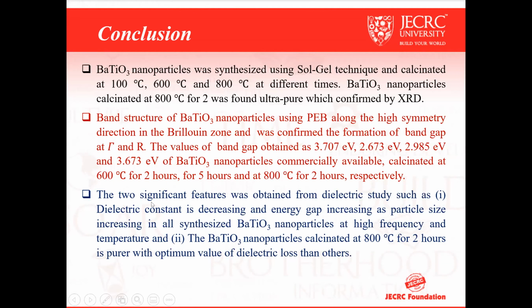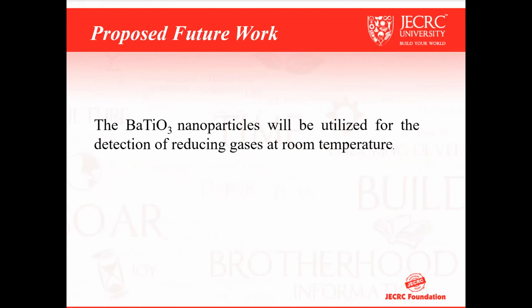The major conclusions drawn from the dielectric study: the dielectric constant decreases and the energy band gap increases as the particle size increases in all synthesized barium titanate nanoparticles, across frequency as well as temperature. And second, the barium titanate nanoparticle calcinated at 800 degrees centigrade for 2 hours is very pure and has an optimum value of dielectric loss compared to the others. On the basis of this, the future work is that this nanoparticle calcinated at 800 degrees centigrade can be utilized as a sensing material for the detection of some gases at room temperature.